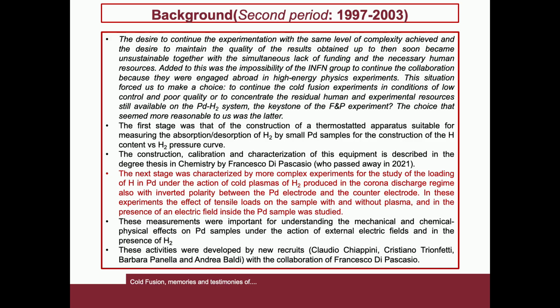The first stage was that of the realization of a thermostated apparatus suitable for the measurement of the absorption and desorption of hydrogen from small-sized palladium samples for the construction of the hydrogen content curve versus hydrogen pressure. The calibration and characterization of this equipment is described in the degree thesis in chemistry by Francesco Di Pascasio, who passed away in 2021.